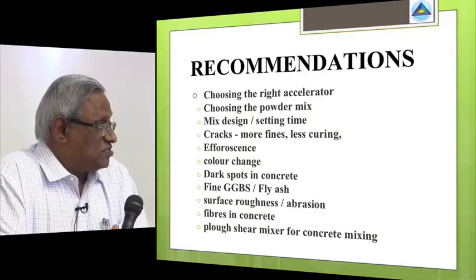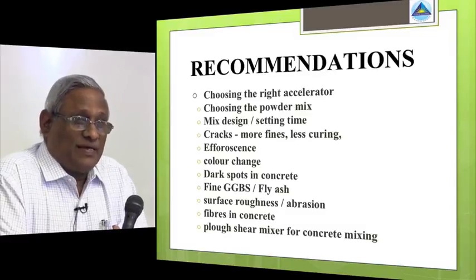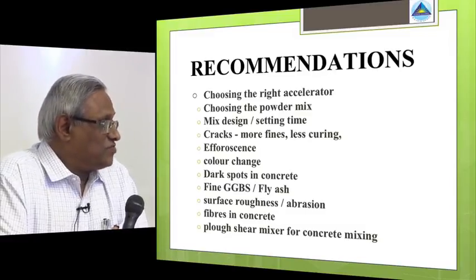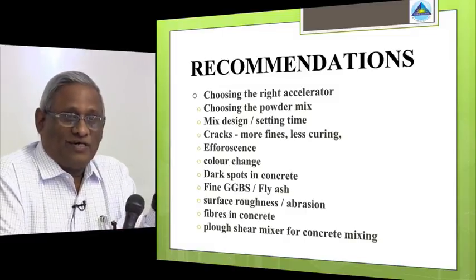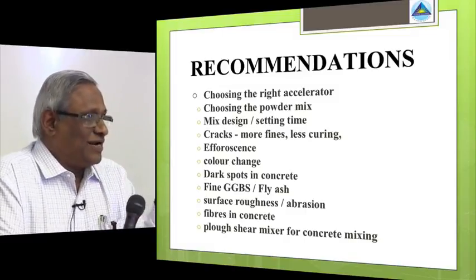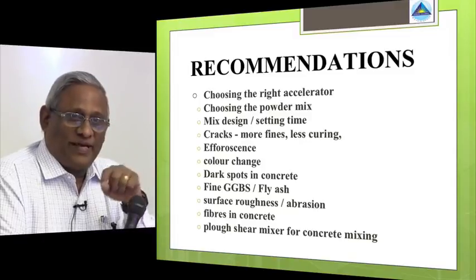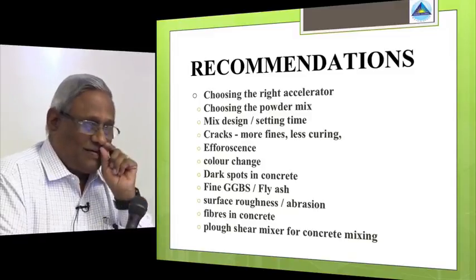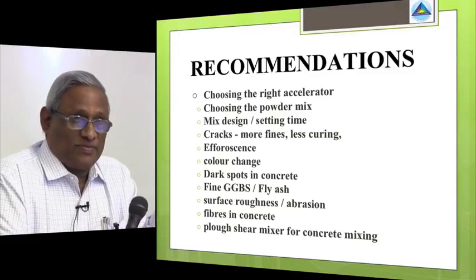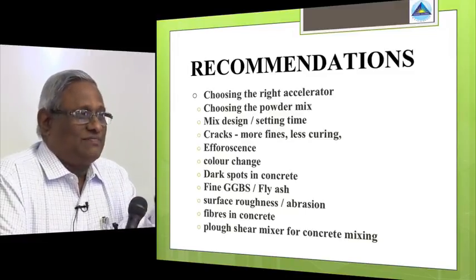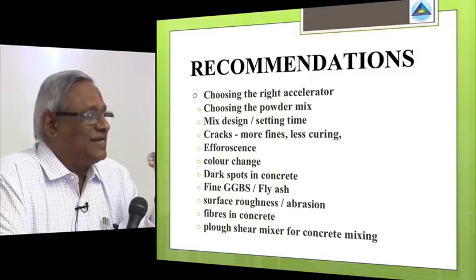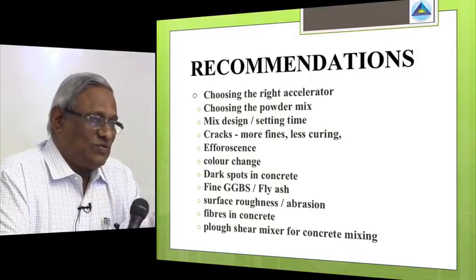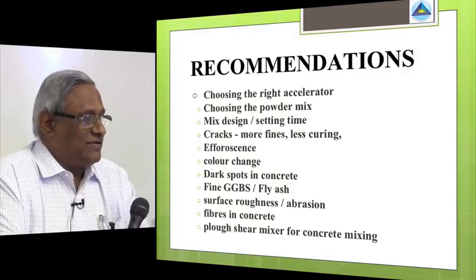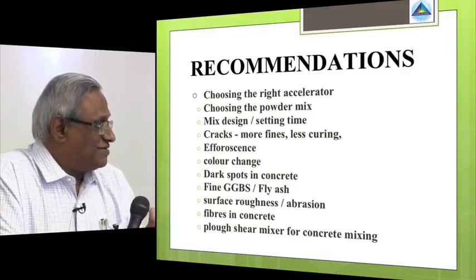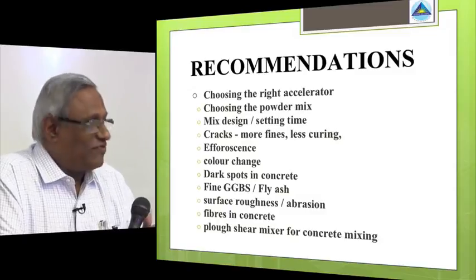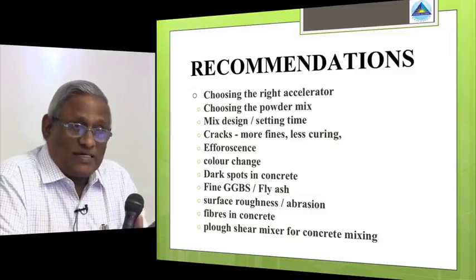Another important problem is the efflorescence. It happens when you use a higher alkali. You get white spots or different types of things that come out, and you will feel this when you put the product in water. And you measure the pH, you know how much additional alkali your product has consumed. Actually, it is possible to optimize and work with a very low amount of silicate activator. When I attended the conference in 2013, they said we used to have 22% alkali. Now we work with 5%. There are dark spots in concrete.